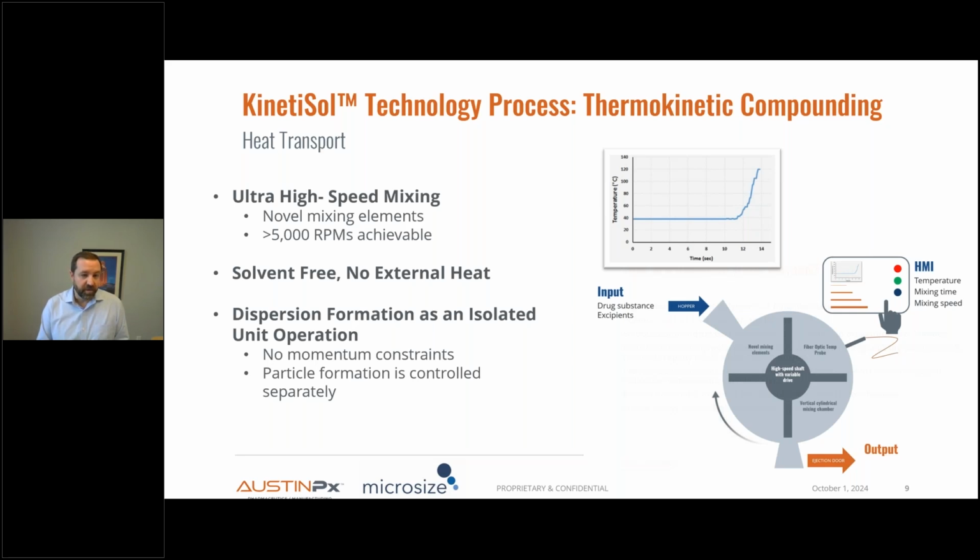KinetiSol is a thermokinetic compounding technique that utilizes ultra high speed mixing elements that operate at extremely high speeds, producing significant amounts of shear. This is a solvent-free process. This shearing and frictional heating that occurs when these blades impart energy into the product produce the heat directly and allow for the material to rapidly heat up and produce an amorphous dispersion. And you can see from the inset graph that this would occur in about 10 to 15 seconds, depending on the process or the product. And most of that time is in the initial induction phase. The heating that occurs is very limited.